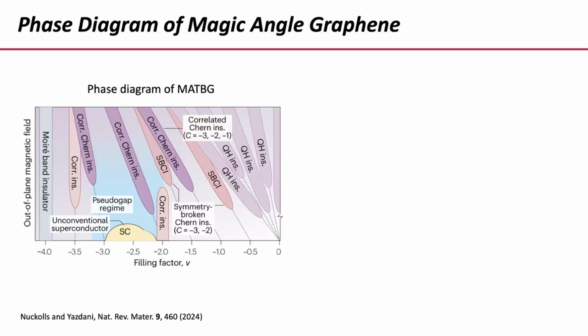Now, something that has been a little bit difficult in this field is that because there are many competing many-body states close in energy, and because you also have some inherent disorder, for example, twisting disorder, although the basic features have been reproduced many times by many groups, sometimes doing detailed comparisons between different devices or different regions of the phase diagram, okay, has turned out to be a little bit difficult. And that means that some things that you can find with one technique, it's harder to see with the other and vice versa.